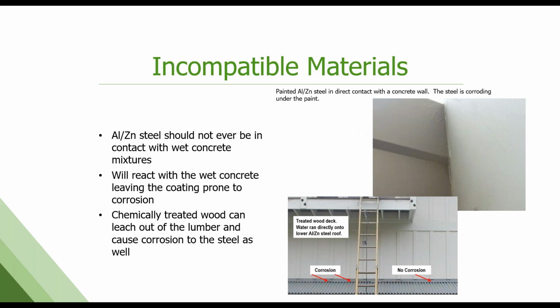These are some other examples, right? So the Galvalume, the aluminum zinc steel, cannot be in direct contact with concrete. The water and the moisture that it holds will corrode that aluminum and zinc mixture pretty quickly. An example there at the top where they did a concrete pour up against the panels without putting a barrier between them, and you can see all the paint's bubbling and lifting off. That is because underneath the paint, the panel is corroding, the steel is corroding.